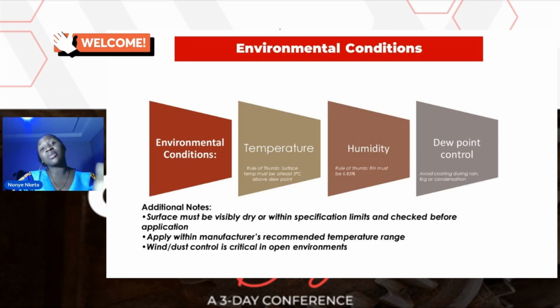Then the next slide is environmental condition. This is the part that most people often overlook. You're just ready to coat, and you're not even wondering if the environmental condition is suitable for the product you want to apply. The temperature, as a rule of thumb, we know that surface temperature must be at least 3 degrees above dew point. 3 degrees above dew point. Do we really check? Sometimes you see some people, they will tell you, okay, we can do this job at midnight before the asset owner comes.